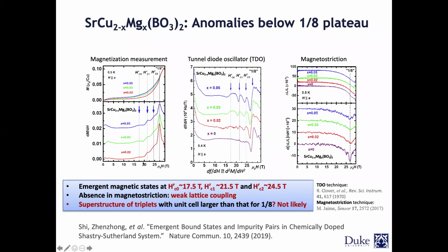To our very surprise, here is what we started to see. This is the same 1/8 plateau that you saw before. This is dM/dH, so I'm taking a derivative for you to be able to see it better. This is for the 2%. You can see that the 1/8 is there, agreeing with what we saw before, but there is a wiggle happening here. In the 3%, the wiggle is even more. At 5%, it's even more.